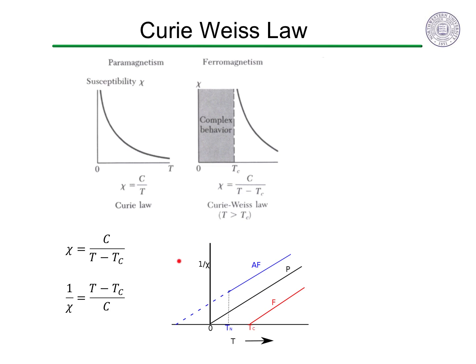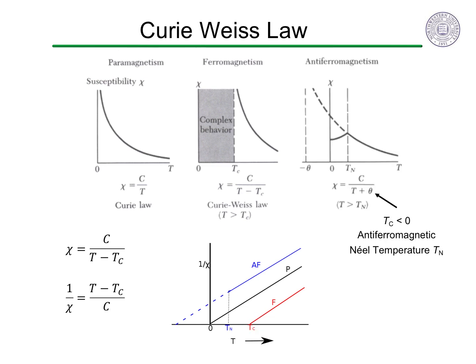The inverse susceptibility looks like a straight line with an intercept, the slope being the Curie constant and the T-intercept is the Curie temperature. Whereas a paramagnetic material has a 1 over chi intercept at T equals 0, a ferromagnetic material will have a 1 over chi intercept at the ferromagnetic Curie temperature. An antiferromagnet has a 1 over chi that is a straight line heading towards a T-intercept less than 0. This is because the interaction is such that the spins are trying to anti-align their neighbors, so that the Weiss molecular field parameter is negative.